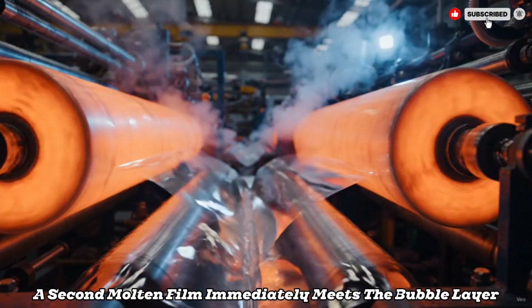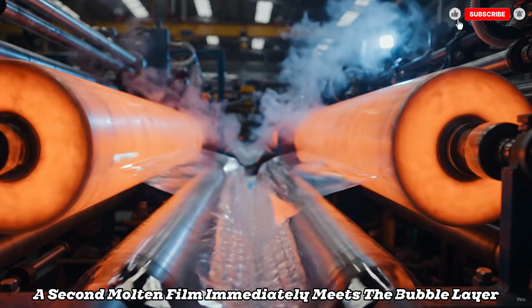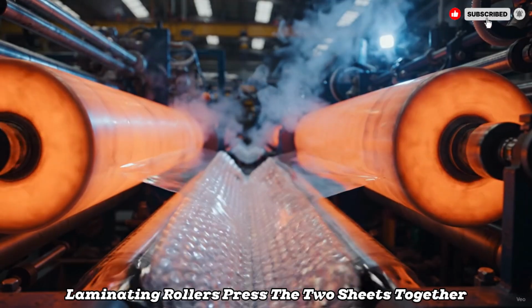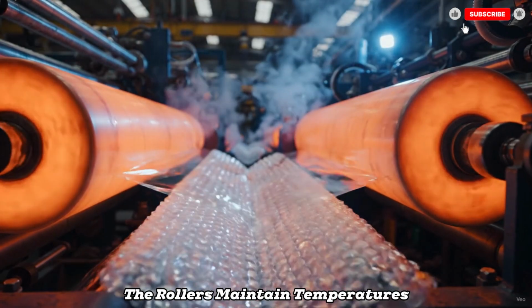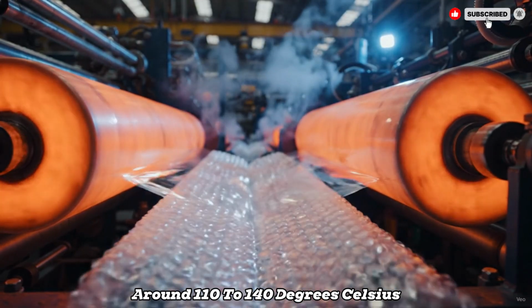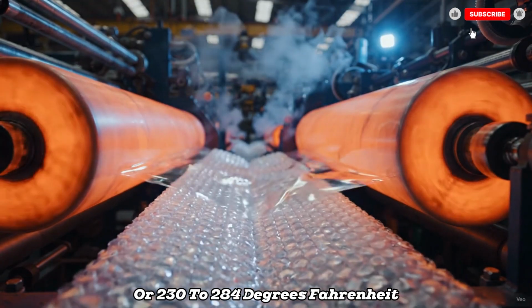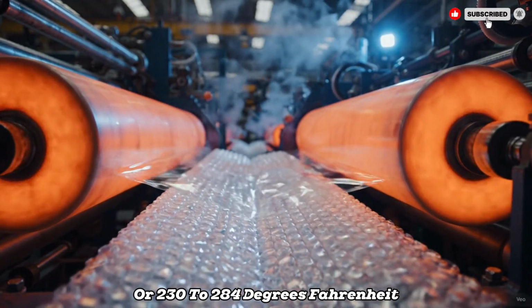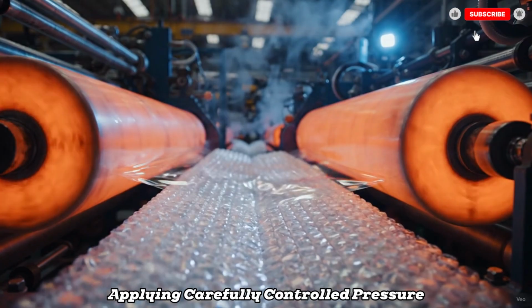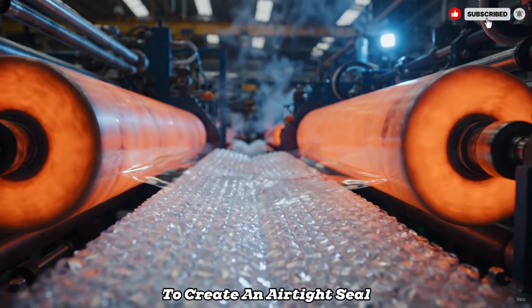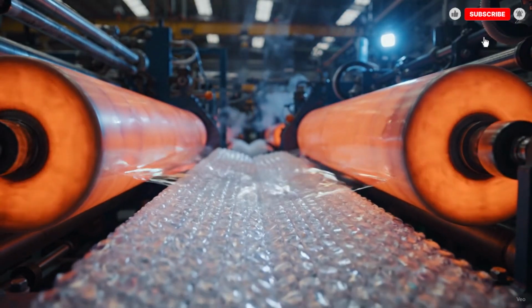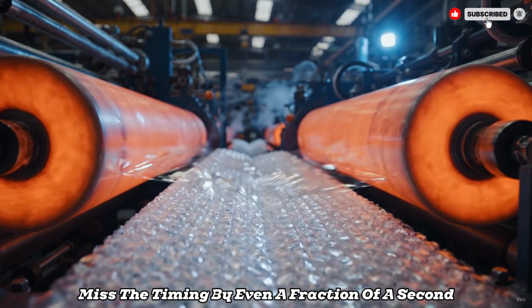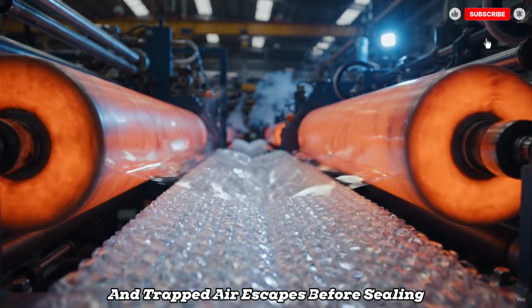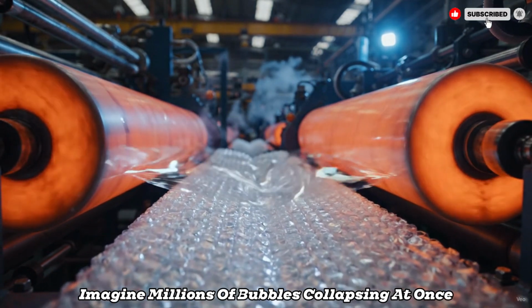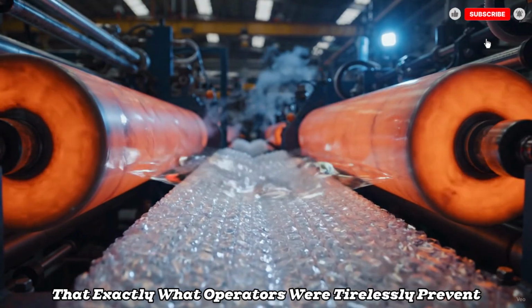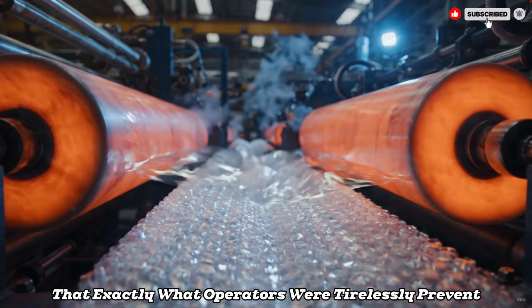A second molten film immediately meets the bubble layer, while heated laminating rollers press the two sheets together. The rollers maintain temperatures around 110 to 140 degrees Celsius, or 230 to 284 degrees Fahrenheit, applying carefully controlled pressure to create an airtight seal around every single bubble. Miss the timing by even a fraction of a second, and trapped air escapes before sealing. Imagine millions of bubbles collapsing at once. That's exactly what operators work tirelessly to prevent.